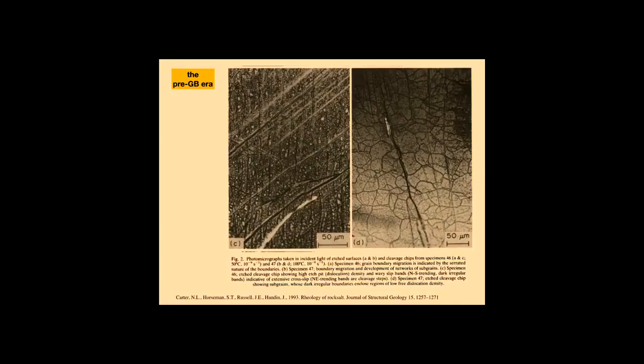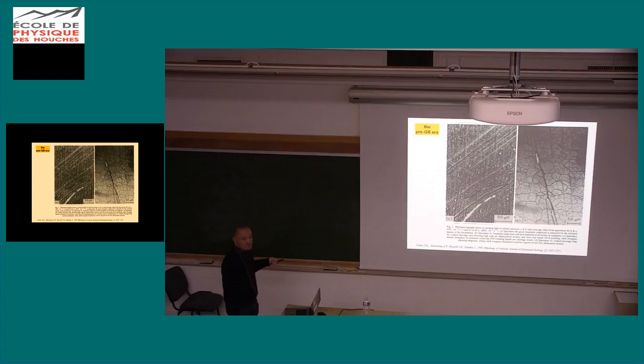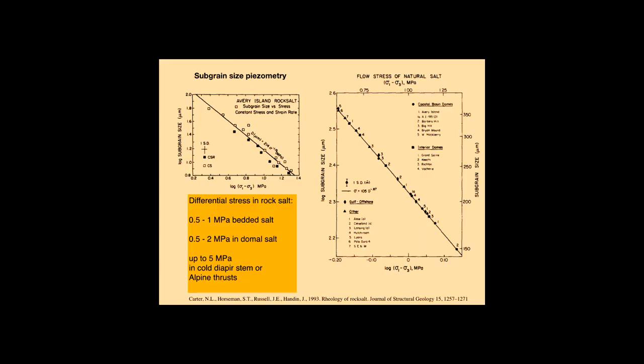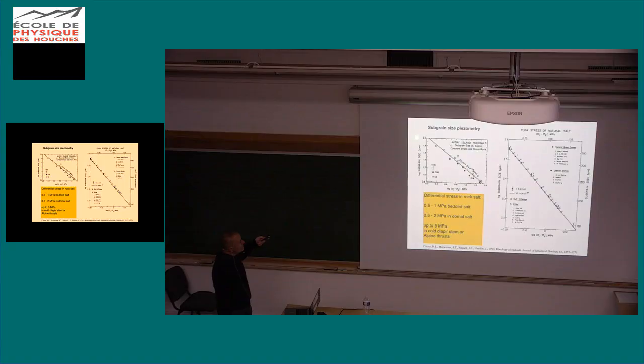So what they did is they broke the samples, and they took small crystals out of it. It was quite an amazing kind of work. And then they etched these crystals, and they demonstrated that there were lots and lots of dislocations, subgrain walls, all the beautiful networks which were formed there. And this was important because they basically laid the basis of subgrain size piezometry. They showed that there is a very, very nice relationship between the differential stress and the subgrain size, and this was then applied to natural rock salt.